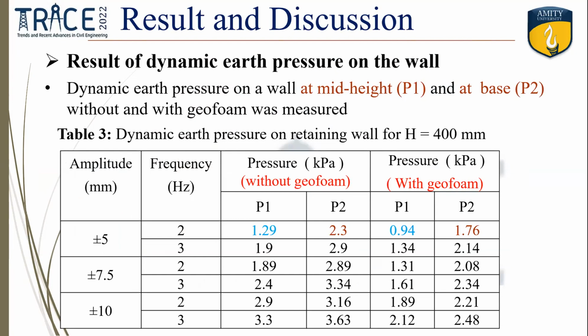Result and discussion. Result of dynamic earth pressure on the retaining wall. As we can see, the pressure is measured at mid height, which is P1, and at base, which is P2. Table 3 shows the dynamic earth pressure on the retaining wall for the given amplitude and frequency in hertz. We can see that the value of P1, which is at mid height, is 1.29, and when we use the geofoam, it is reduced to 0.94. There is a reduction in dynamic earth pressure when we use the geofoam material. The same trend is followed for the P2 force.